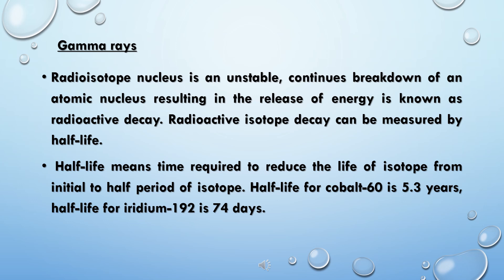Radioactive isotope decay can be measured by half-life. Half-life is the time required to reduce the activity of an isotope to half of its initial value. The half-life of Cobalt-60 is 5.3 years, and the half-life of Iridium-192 is 74 days.